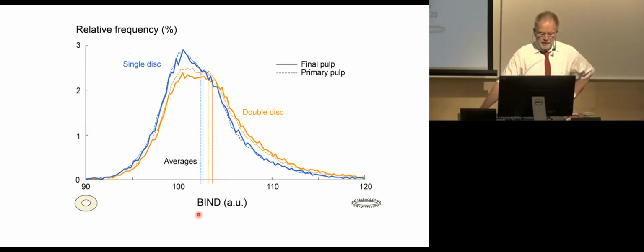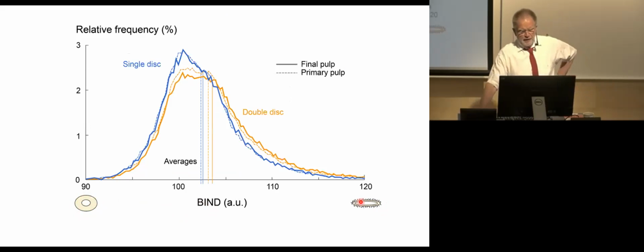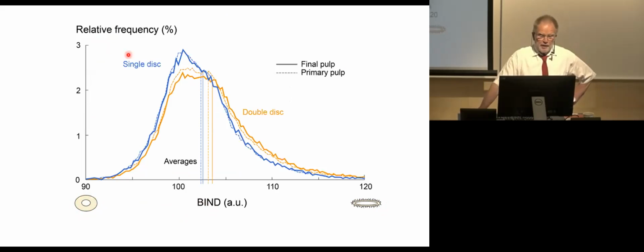Looked like this. Here I have the BIND. Here you have the very stiff particles. You saw the thick-walled fibers. And here I have fibrillated collapsible fibers. And on this axis, you have the relative frequency. And then we have dealt with single disc refiners and double disc refiners.